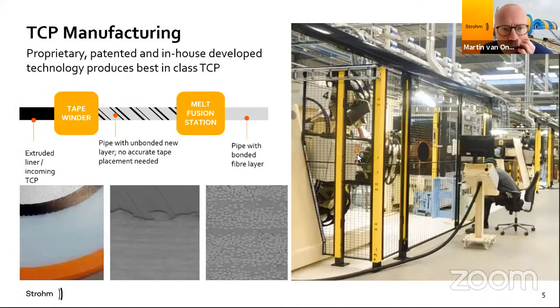So what we do is we actually always create one full layer. What you see here is exaggerated. Can you see this or not? Yep, I can see it. In principle, what we do, and I think I understand maybe what you mean, I know one of our competitors does this differently. Our tapes are in principle so wide that per pass, we create one full layer. And our melt fusion station is designed such that if there is, for instance, a space, that space disappears in the melt fusion station. So after the melt fusion station, the whole pipe is without spaces and without voids.